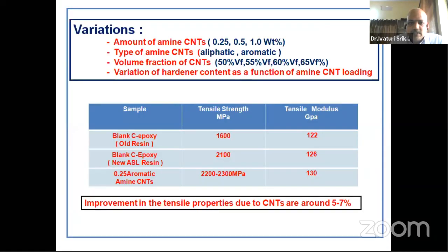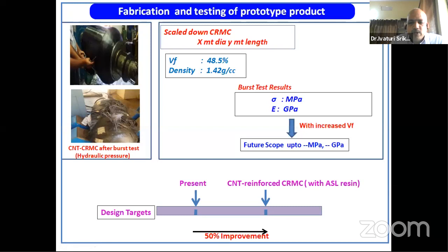Now, to this resin system, we added the CNTs. As I told, we have tried different types of functionalization. We tried aliphatic and aromatic amine functionalized CNTs. We tried different volume fractions and fiber to volume ratios. We had a lot of variations. The improvements due to CNTs are only less than 10%, whereas the improvements due to the changes in the resin system are significant. So what we realized is that nanotubes as such cannot give a significant improvement in the tensile property.